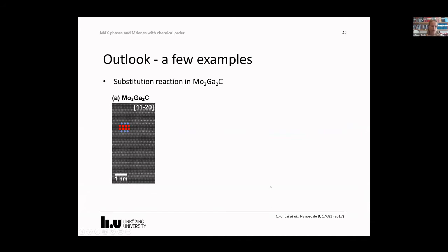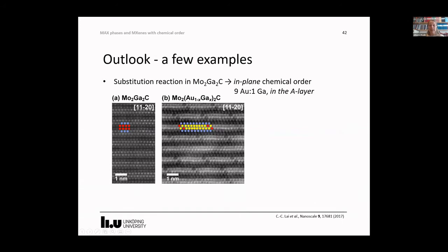I will end with a few examples of what I think lies ahead of us. So far, I've talked about chemical ordering of the M elements, but here is another example, a substitution reaction in Mo2Ga2C. If we have a film of this material, with gold as a capping layer, and then we heat it up, we remove almost all gallium and we get gold in there instead. But we get 9 gold to 1 gallium, which is chemically ordered in the A layer, as you can see here. This is not something that we have looked into at all.